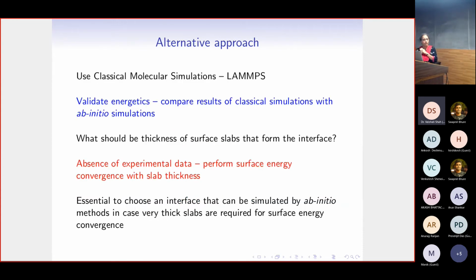So then we thought, let's find an alternate approach where we do not work with first principle simulations, but we perform classical molecular simulations where we are able to handle a very, very large number of atoms, so this number of atoms should not be a problem. However, if we want to use this approach, we need to first validate that the calculation we are performing by classical approaches is giving us the right answer. And to validate, we have to again resort back to first principles methods because they are more accurate and typically have a better agreement with the experimental results. So we must be able to compare the results from the classical simulations with ab initio simulations, one.